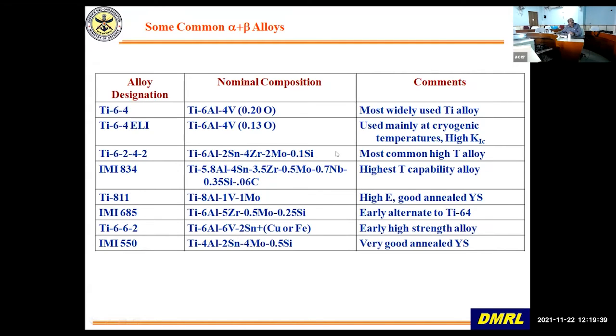This can be used up to a maximum of 500, 525 degrees centigrade. This can go up to a maximum of 550 to 600 degrees centigrade temperature. These are older generation alloys which are there. 811, IMI 685, which was used in older engines, etc.